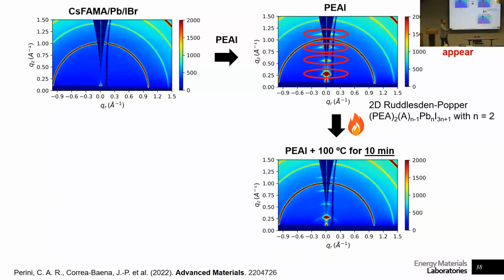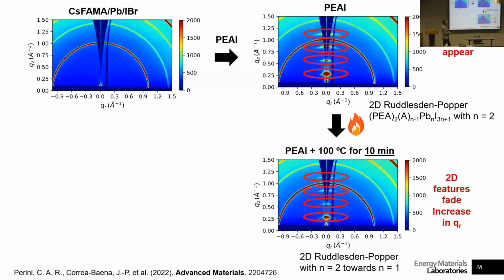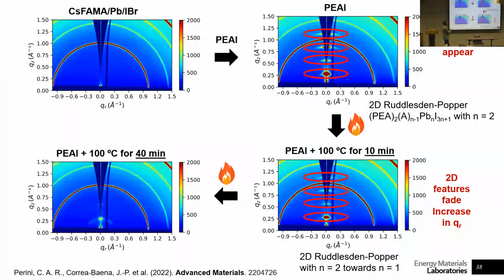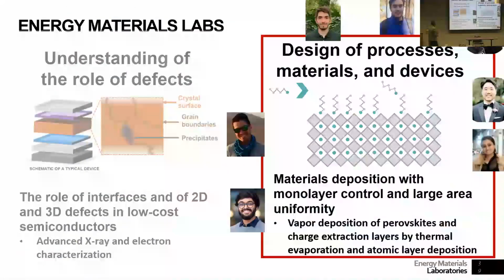We expose them to different environments. So here, for example, we expose them to heat and try to see, are those features surviving? And we see that they're not. So how stable are those features? How stable are those chemistries? And then, for example, after 40 minutes, we see those features completely disappearing. So this allows us to probe the intrinsic stability of the materials before we even put it in a solar cell, because we want to make sure that the material itself is stable before we actually test it in a solar cell. So we do a lot of those studies at the synchrotron.